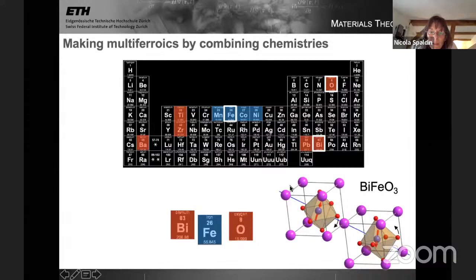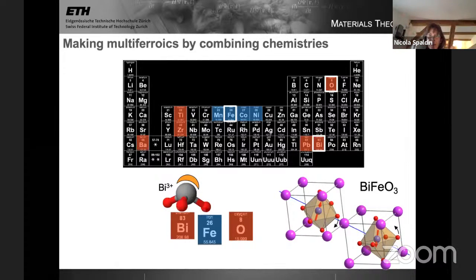And the bismuth, trivalent bismuth, is ferroelectric because it has a lone pair. If we take 3 electrons out of bismuth, it has a pair of 6s electrons, which is stereochemically active. This lone pair, rather than staying spherical like 6s in a sphere, localizes on one side of the bismuth and makes a dipole, just like, actually this picture is ammonia, right? Just like the lone pair of electrons on the nitrogen in ammonia, the 6s electrons on the trivalent bismuth localize. Of course, it mixes in some p character to do that and makes a dipole. It's negative, the bismuth is positive, and so it introduces a dipole.